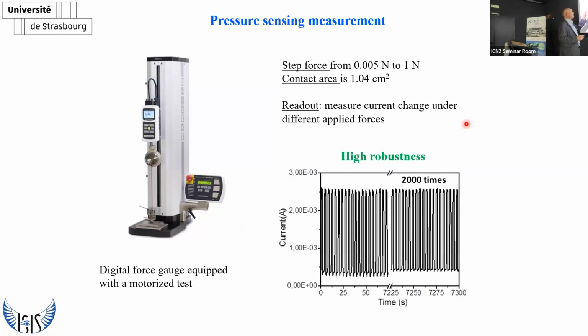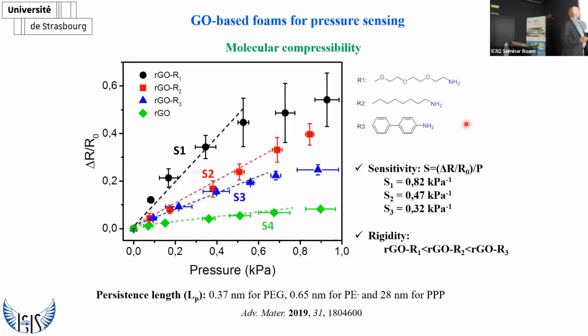And we tested it in the lab with a force gauge. This is the most important plot of this study, where we look at how, upon application of pressure, the resistance divided by R0 changes. You can see that there is a bigger change when molecule number 1 was used, the most flexible one, and the smaller change when 2 and 3 were used, and 4 is a pure GO-based device. So in other words, when you use a flexible molecule, you have a higher sensitivity. The sensitivity scales with the persistence length of the molecule, a parameter used in polymer physics to quantify the rigidity of polymer chains.